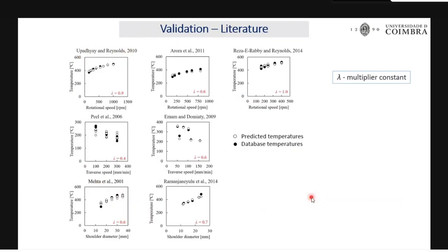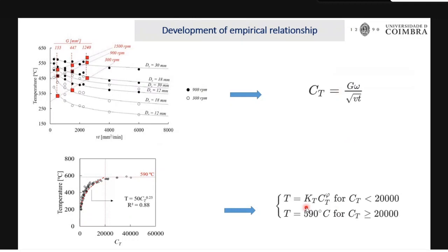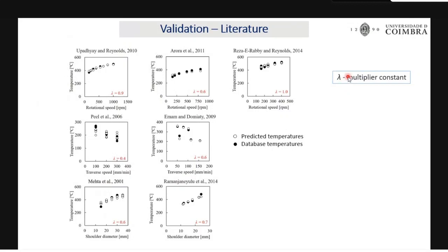The robustness or reliability of that equation is verified with the literature. The dark circle is the database temperature, that is the literature, and the unfilled circle is the temperature predicted with the previous equation. You can see you have a very good match. And in order to get a better fitting, I also multiplied this KT and this phi value with a multiplier, because each author uses different measuring techniques and different measuring locations.